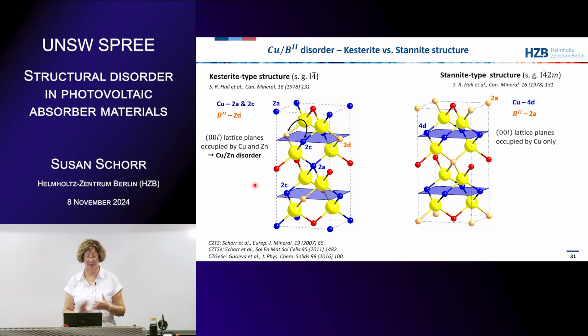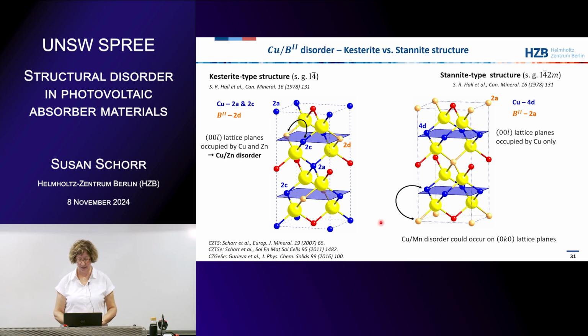So when we now go to the stannite type structure, we have these copper planes here and also here. Within these planes, we will have to exchange with another ion. For instance, we could exchange with this divalent cation coming up to that position, and then we also would have a disorder. Now the question is if this happens in stannite type materials.